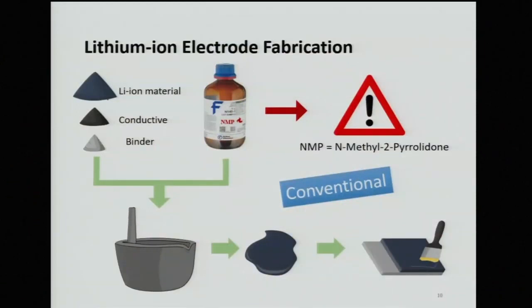Well, that's because of the binder. The binder is highly specialized because it doesn't degrade during battery use. It's also very picky. It only wants to dissolve in NMP. And we need it to be able to dissolve in NMP so we can make a uniform coating among these three components. That actually brings us to the second reason why this conventional technique isn't very appropriate.